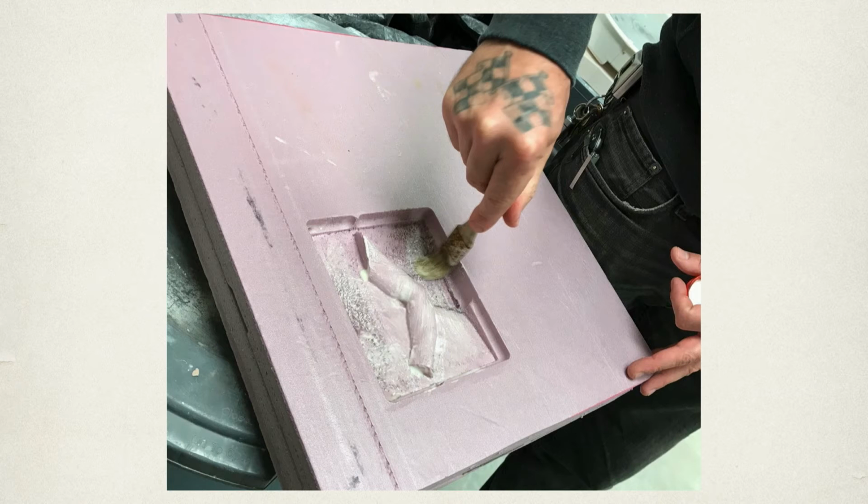So we've done a little experiment. I was a little concerned with release. I'd read some horror stories about getting these things off, but it worked pretty well. There are products for coating, Styrocoat that Smooth On makes for coating these types of foams that won't eat the foam. That's another thing about working with this foam, and of course the advancements in resins and binders are pretty amazing, because there are companies that make CNCs specifically for cutting foam, but they present foam as a way and then coating that foam to be essentially outdoor-worthy sculpture, right? So then the styrofoam becomes a finished product. There are materials, obviously the Styrocoat we could get to seal that mold if necessary. I didn't want to put another layer that was going to obstruct any kind of detail, so we just experimented and the soap seemed to work fine. Just a very thick layer of soap.